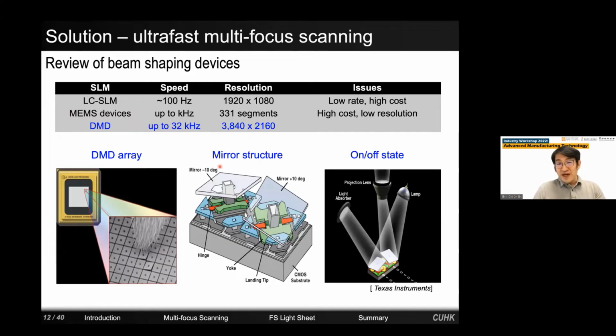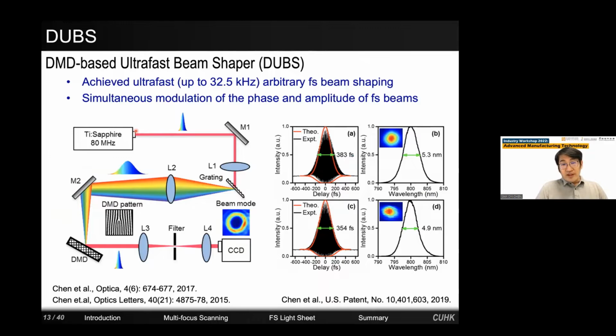Each mirror is a binary display. It only has a plus or minus 12-degree position. So when we combine a DMD with the femtosecond laser, it becomes an ultra-fast scanner. What we do here is we design specific holograms. And because the DMD is binary, we design binary holograms and place them on the DMD. Then the femtosecond laser is introduced to the DMD as a reference beam. As a result, the designed hologram is recreated here.